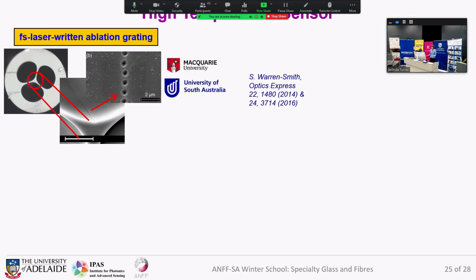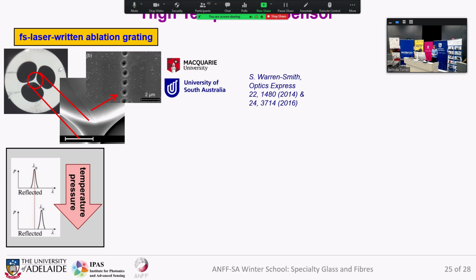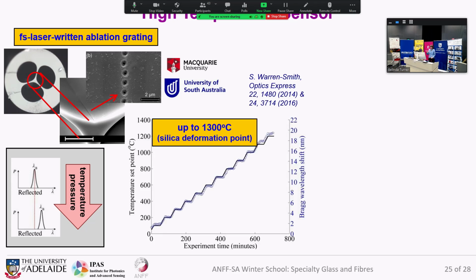High temperature sensors are an example of nano or microstructuring. We use a silica suspended core fiber, made only of glass. We create tiny air holes into the surface of the core with a femtosecond laser, again an air-glass structure. These holes act as a grating, and only a certain wavelength is back-reflected, with the wavelength of the reflected light sensitive to temperature. Silica's deformation point is 1300 degrees Celsius, so we can go up to this temperature.